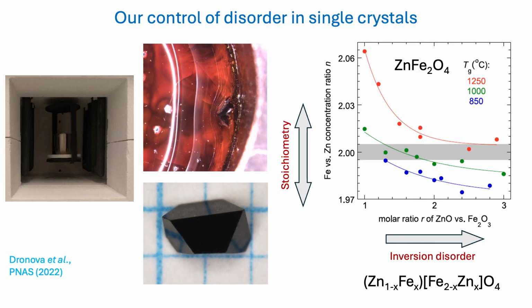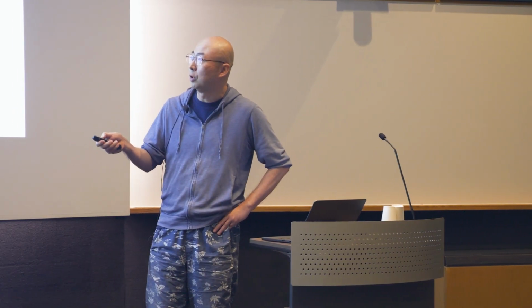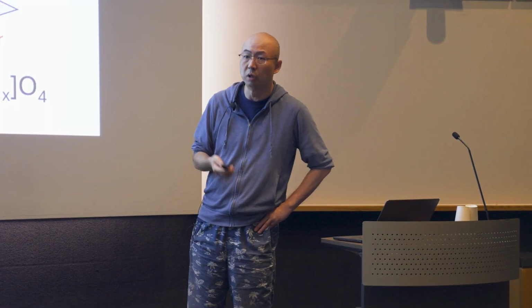So you have control. Second, we have different growth temperatures, from high to low. When you go to high temperature, you need to put in lots of zinc to make it stoichiometric, but that creates lots of inversion disorder in this crystal. However, if you grow at a low temperature, you can put in less zinc, much closer to the stoichiometric condition, and you have a much more stoichiometric material and also a low level of inversion disorder. So with two control parameters, molar ratio and temperature, we can fight against off-stoichiometry and inversion disorder simultaneously.